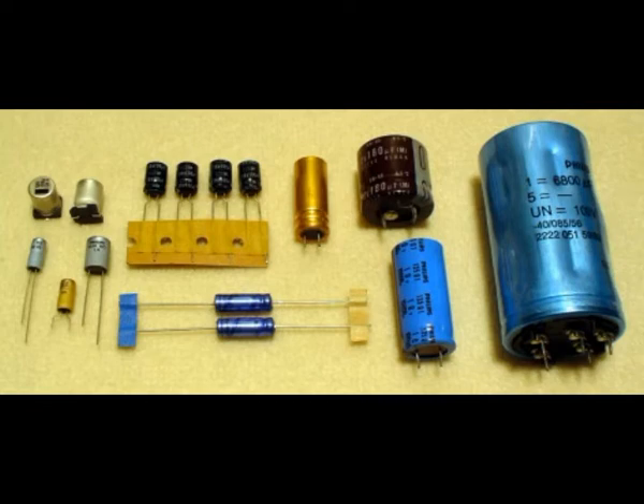Thus, the capacitor construction forms a series circuit of two capacitors, the capacitance of the anode foil C_A and the cathode foil C_K. As described above, the capacitance of the capacitor C_e cap is mainly determined by the anode capacitance C_A when the cathode capacitance C_K is approximately 10 times higher than the anode capacitance C_A. Aluminum electrolytic capacitors with non-solid electrolytes normally can be charged up to the rated voltage without any current limitation. This property is a result of the limited ion movability in the liquid electrolyte, which slows down the voltage ramp across the dielectric, and the capacitor's ESR.